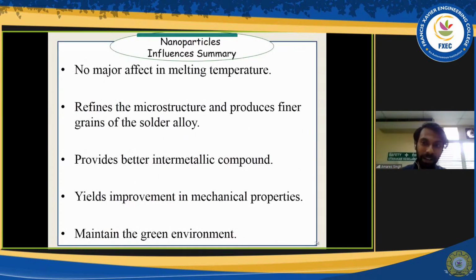So what does this whole literature review give us in terms of a hypothesis? There is no major effect on the melting temperature. The microstructure is said to be finer, producing a better intermetallic compound layer in terms of a thin IMC layer, and yielding improvement in mechanical properties. We saw the hardness and the shear strength increase. Of course, we are using lead free, so it maintains lead free as long as we don't add plumbum nanoparticles, right? So it's a lead free solder alloy.